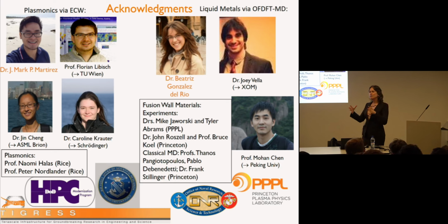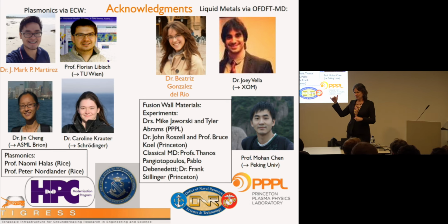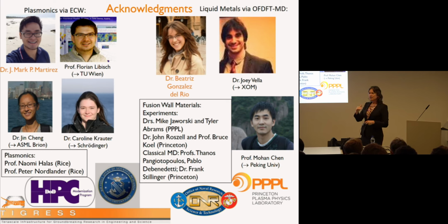We've also explored, and I can tell you that, we thought, well, maybe along the reaction path one should allow that embedding potential to change. That introduces lots of mischief, as it turns out. What we found gives the most robust results is to solve for this embedding potential for the bare metal. Because metals screen things well, we think we're fine, as long as the cluster is big enough, once we bring up the molecule involved in the chemistry. We don't get nice potential curves if we re-optimize the embedding potential along the way, because you're changing the Hamiltonian in a way which is not controllable.